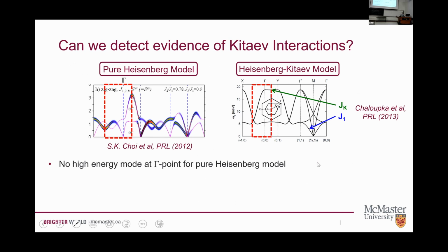We can then compare it to different theoretical models. So I'm showing you here sort of two simple models. The pure Heisenberg model, this one's got 3 different Heisenberg exchange terms for nearest neighbor, next nearest neighbor terms. And then one model that involves Heisenberg and Kitaev terms. And the big difference between them is this mode up here, this high energy mode that peaks at one position in momentum space that we call the gamma point. Okay, so you only get this high energy gamma mode if we include the Kitaev term.